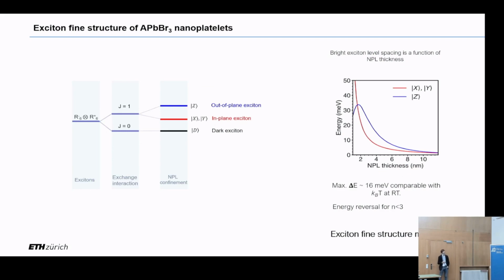And a final observation, which is quite interesting and specific of lead halide perovskites, is that since they have a very small Bohr exciton radius, the exchange interaction is very strong. It cannot be disregarded. And that's what leads to singlet-triplet splitting of the band edge exciton. And not only that, but the shape of the nanocrystals effectively affects the fine states that compose the triplet state. And the interesting part here is that, as you can see, these are the out-of-plane and in-plane states which get split by the anisotropic confinement, and the difference between them is thickness dependent and is up to 16 meV, and that's very, very close to kBT at room temperature, which means that we would observe such effects on the population of states even at room temperature.